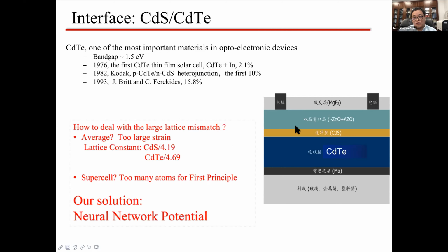It is not so easy to do real simulations because these two systems have a very large lattice mismatch. It cannot easily be done in a real simulation by first principles, because if you build a supercell, there are 2 million atoms. So our solution is that we need to use a neural network potential. Now it has become very popular for material science simulation, or one can say it is one of the best examples of AI in computational material science.